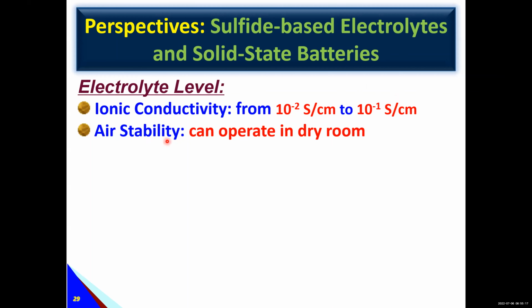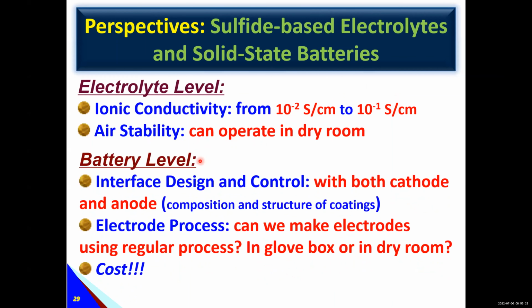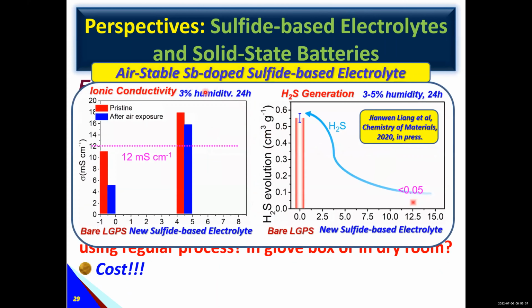And also air stability is important for synthesizing solid state electrolyte. For battery level, we need to control the interface. As I mentioned, the electrode interface is very important. So actually, when we talk about air stability, we also work on that. We dope antimony in LGPS. We found it not only increases ionic conductivity, but also increases air stability. With this doping, we can reduce H2S a lot. Also, we can dope other elements to try to increase air stability.